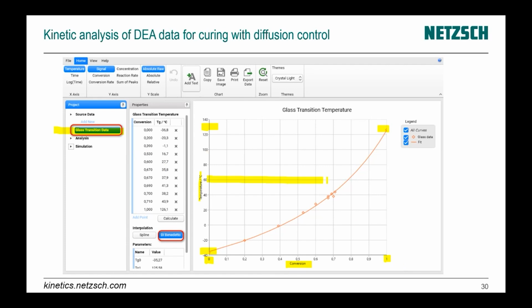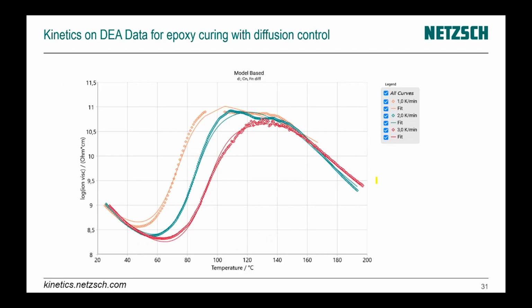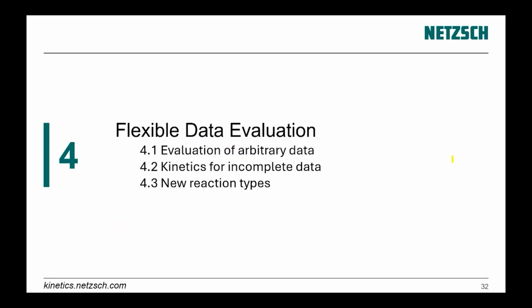And during isothermal curing, we see that at the beginning, our sample temperature is above glass transition temperature, and we have fast curing. And then we have a crossing with the glass transition temperature, we have vitrification, and afterwards we have a sample temperature below the glass transition temperature. We have the curing in vitrified state, and this curing is really very slow. And now we can do this for DEA data and for rheology data. And here we have some very nice example where it works.